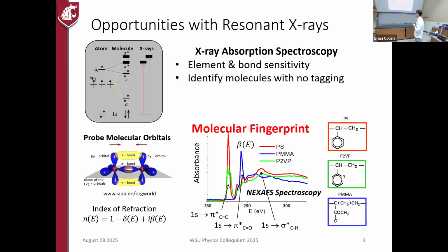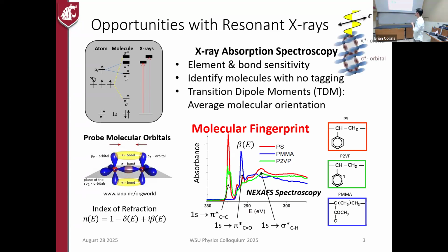This is absorbance versus photon energy at about 300 electron volt photons versus your 1 electron volt of optical photons. You can see a step here where that's the photoionization edge of the carbon atoms, the photoelectron coming off. But if we resonate right at the step into these molecular orbitals, we can get really big enhancements in the absorption, very localized in energy, that represent different bonds within that molecule. And so that's the bond sensitivity, so we can tell different polymers apart, even though they're made of the same elements.